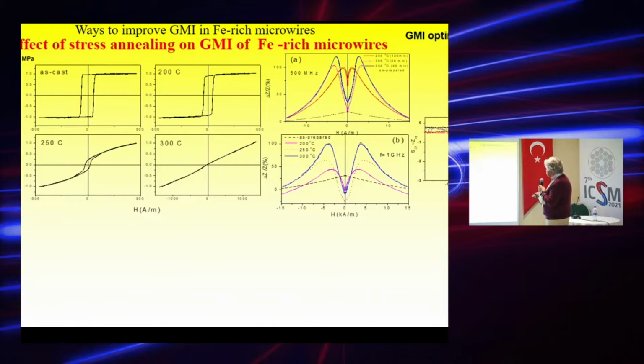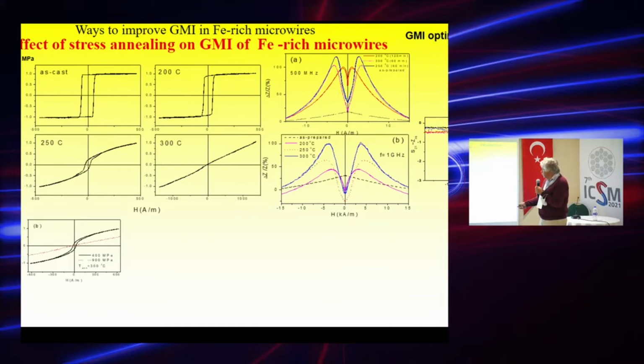And of course, not only the GMI ratio, but also the diagonal component could be drastically improved. So this is the diagonal component of the magnetic impedance effect after different thermal treatment. And it also depends not only on temperature, but also on the stress applied during the annealing. Here are two different curves. This is smaller stress and this is higher. So with increased stress during the annealing, the magnetic anisotropy is increased.